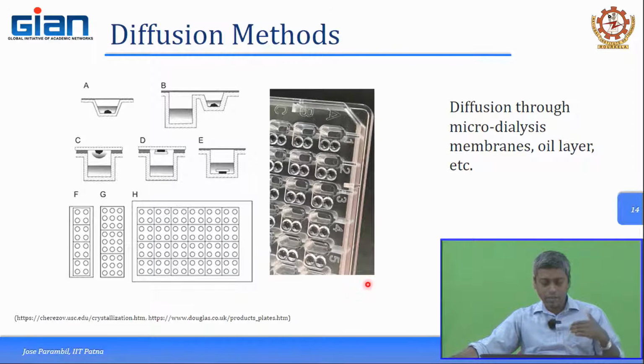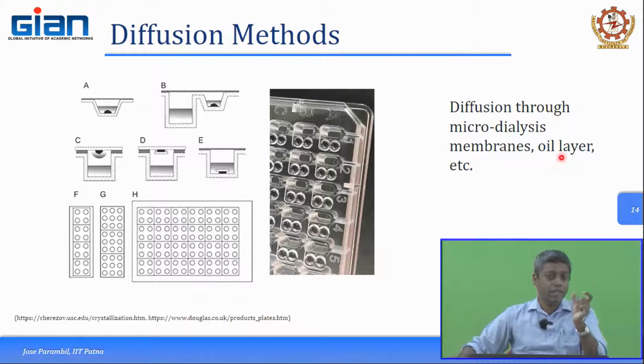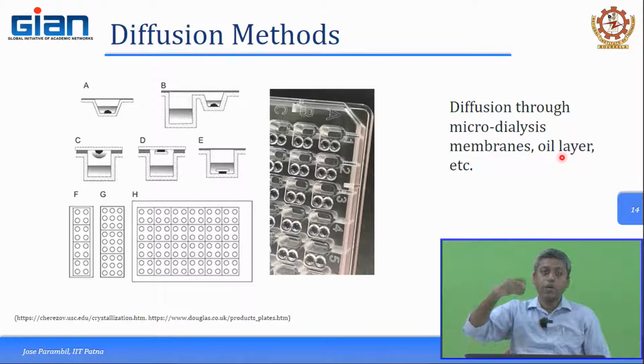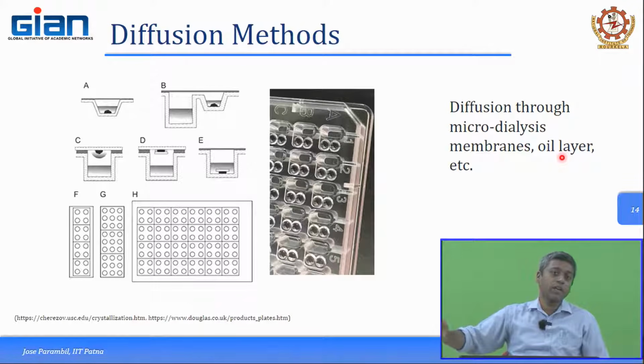But there are other ways as well to control the diffusion and ensure very small changes in concentration. One of the common methods which is often used is called microdialysis membranes, or you could even have a small oil layer on top of the droplet in order to reduce the evaporation rate. If you have a little bit of, let us say, surfactants or oil on the top layer of the droplet, that reduces the interfacial area that is available for the water molecules to evaporate. So, it might arrest most of the evaporation.